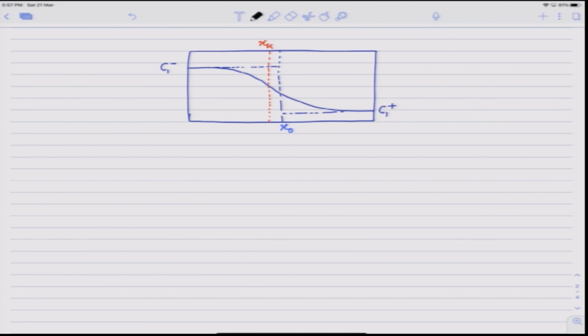Now we know we can write the intrinsic diffusion flux as J1 equal to J1 tilde minus C1 times Vk, where Vk is the velocity of the marker plane. Now out of this we know how to determine J1 tilde directly from the concentration profile. So this all we are considering at the marker position xk, because that is the only lattice plane that we are able to track, because the marker can be placed only at that plane, that is at the initial contact plane.